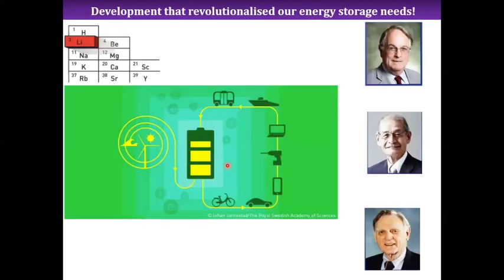So as I mentioned, 2019 celebrated the Nobel Prize for the battery development. And how did it start? It started with these three scientists. Just briefly, I mentioned there was a titanium disulfide material, which was a layered material. And this is lithium. Lithium is the lightest of metals which can be in the solid form and which can be taken back and forth in the system. And they used this principle, the redox intercalation chemistry, to insert lithium and take out lithium during the charge and discharge process to get these rechargeable secondary ion batteries.